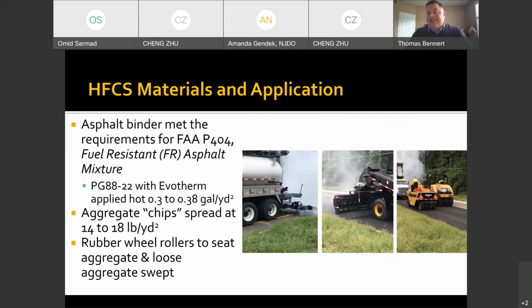Here's just some of the process that we're seeing here. This asphalt binder utilized here actually grades out to what we would call a fuel resistant binder. This is the FAA P404 asphalt material. We did use a warm mix additive in there because what we wanted to try to do is ensure that it was pumpable through their system.